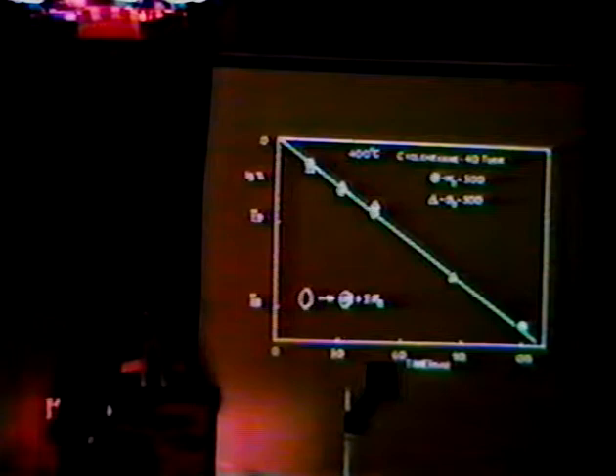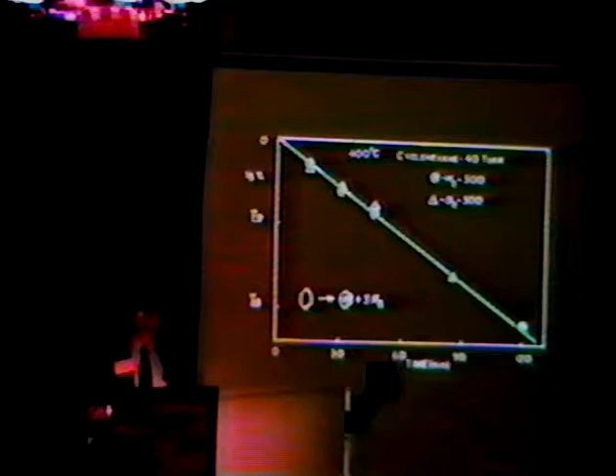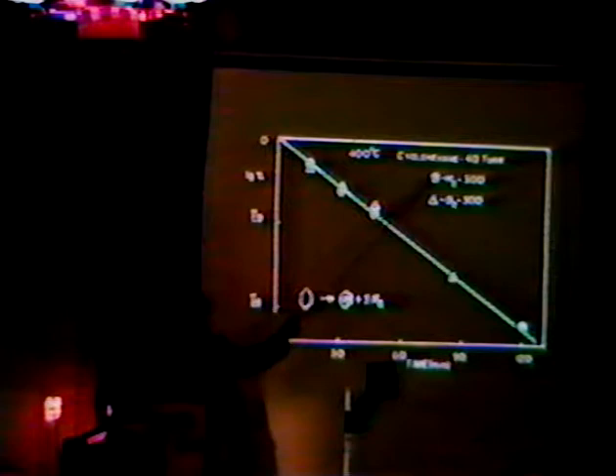Let's take a look at the cyclohexane reaction further. We wanted to find what the mechanism was and what the rate-limiting step is in the cyclohexane reaction going to benzene plus hydrogen. We wondered about the involvement of hydrogen in the gas phase. We carried out experiments in the presence of hydrogen and in the presence of deuterium gas to see if there is any difference. It turns out — this is the log of fractional conversion versus time, a first-order reaction plot — that in both cases the data points superimposed, indicating there is no isotope effect. The gas-phase hydrogen and deuterium apparently were not involved in, or their activation was not involved in, the rate-limiting step.